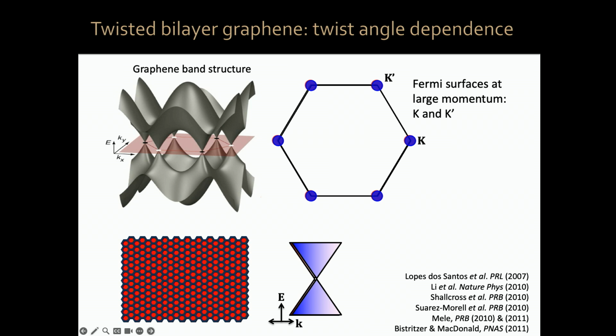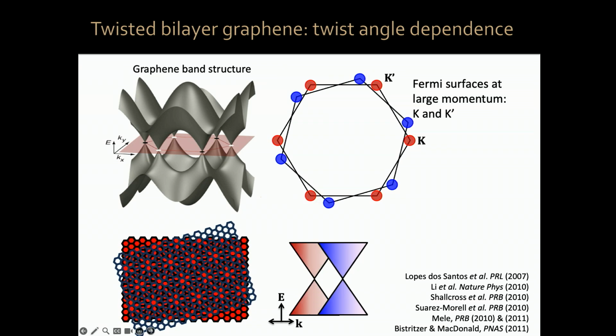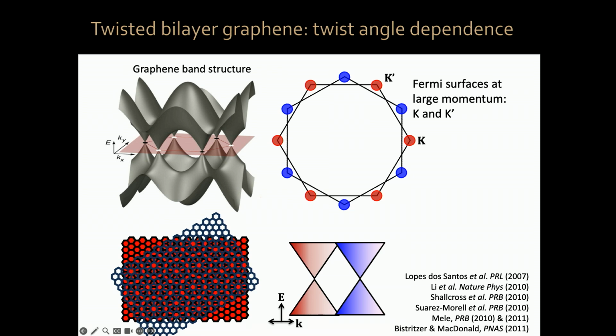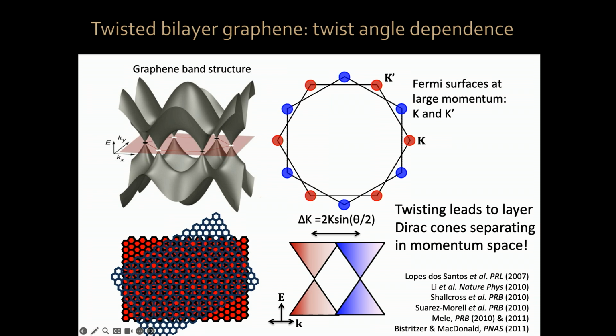If I now rotate one layer with respect to the other, the reciprocal spaces of the two layers also rotate by the same angle. So there is a separation in momentum space between these Dirac points, which is proportional to sine of half the twist angle theta. So twisting leads to the layered Dirac cones, the electronic structures of the two systems, decoupling, separating in momentum space. Let's assume that we start from a small rotation angle.